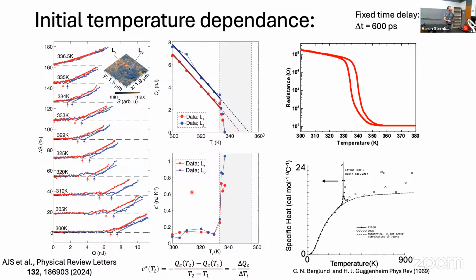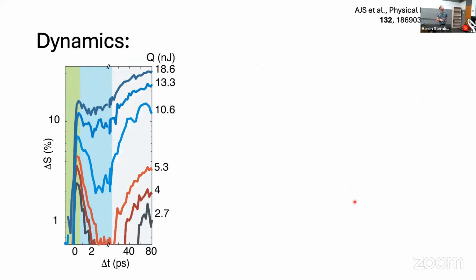Unfortunately, we were unable to normalize and directly compare this quantity, the photothermal capacity, to specific heat. If you could do that, it should be possible to deduce if this is a thermal or non-thermal transition, but it's very difficult to figure out exactly how much volume is impacted by photoexcitation, especially when we have the tip and all of a thin film and so on. And so this connection is only qualitative. Nonetheless, if we plot our data on the same scale, we do see divergence at the same temperature where you observe divergence of the specific heat.